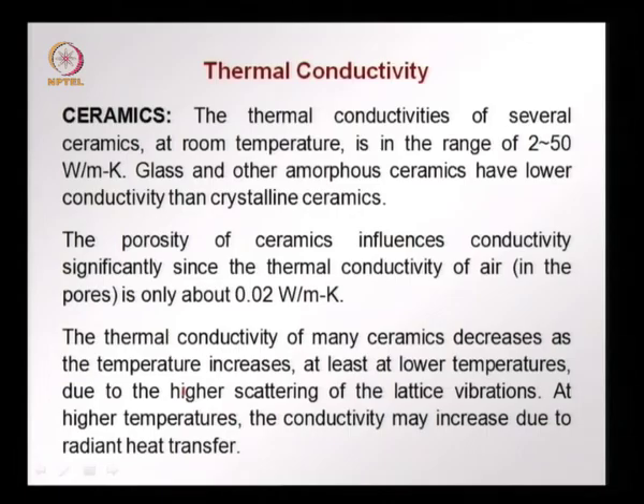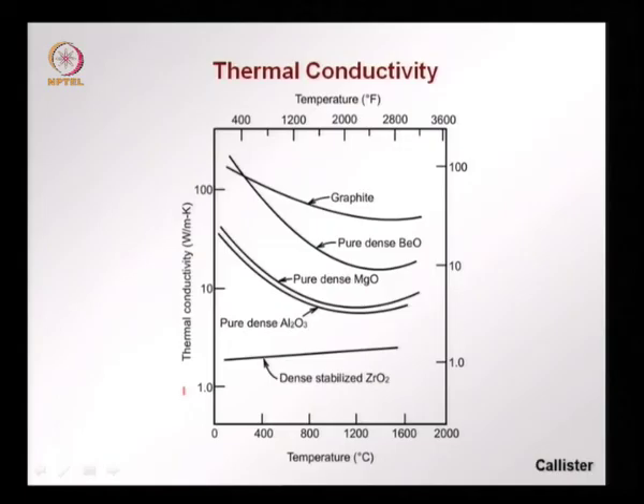Thermal conductivity of ceramics also decreases or can decrease as the temperature increases, at least at lower temperatures, due to the scattering of the lattice vibrations. At higher temperatures, conductivity may increase due to radiant heat transfer. Instead of conduction through lattice vibration, heat could be transferred by radiation. So, here you see how thermal conductivity changes in some materials as a function of the temperature. You can see in the case of a dense stabilized zirconia, you have an increase in the thermal conductivity as the temperature increases. In other cases you have a drop and then the effect of radiation coming in, and there is an increase in the thermal conductivity.